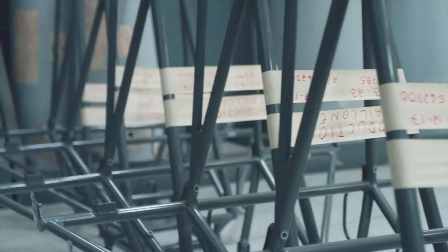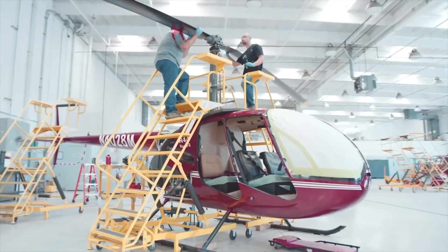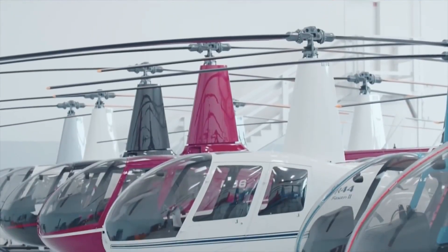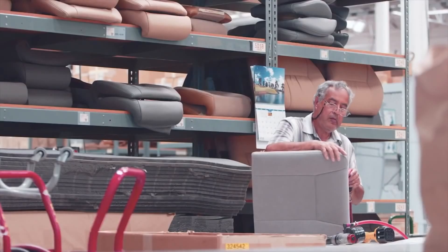Early paddles used a mixture of multiple planks of wood, each with its own characteristics. Wood is a very good blade material because it has no known fatigue life. The wood used included North American spruce, birch vertical laminates with good impact resistance, and tall balsa wood that could maintain the shape of the blades. The blades were covered with fiberglass and sealed with aircraft paint. Due to the poor erosion resistance of glass fiber and wood, a metal leading edge anti-wear wrap was attached to the blade. Making wooden blades requires patience and excellent carpentry skills — all processes are handmade using templates, and a matching set of wood is destined to fly in pairs forever from the moment it enters the manufacturing process.